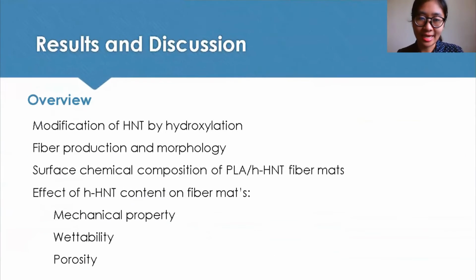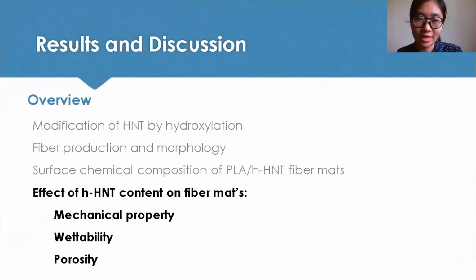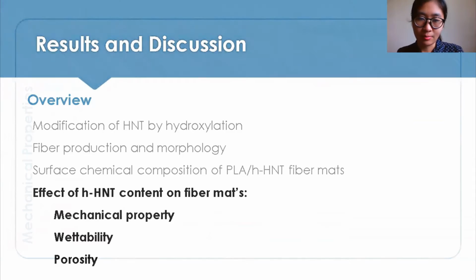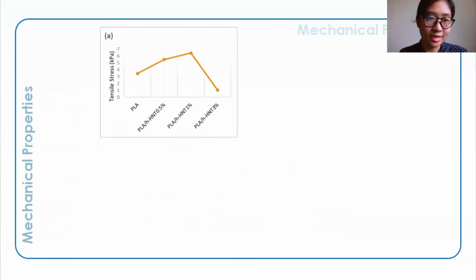So let's now investigate and evaluate the effect of HHNT to the mechanical property of the electrospun polymer matrix. So on the x-axis are the samples, pure PLA and 3 different concentrations of HHNT. In this first line graph, the sample with the highest tensile strength is at 1% HHNT, while the lowest is at 3% HHNT content. So this is the force.